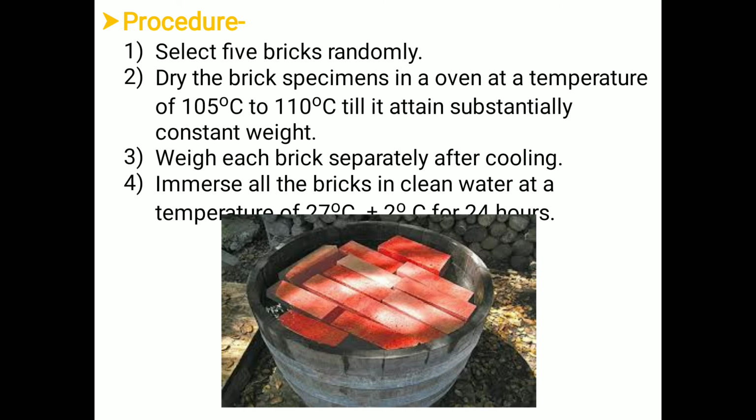The fourth step is to immerse all the bricks in clean water at a temperature of, this is not visible, actually it is 27 degrees Celsius plus minus 2 degrees Celsius, for 24 hours. So as shown in the figure, we have to immerse all those bricks into water for 24 hours. Is it okay?